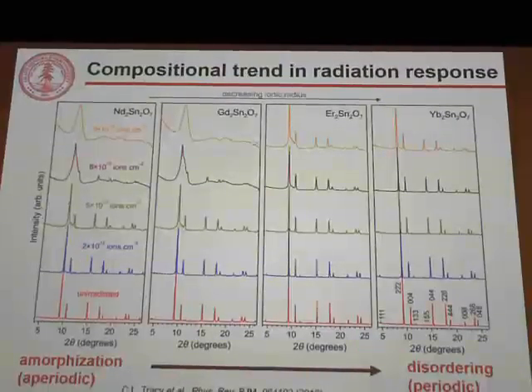Now, there is a strong compositional trend in this radiation tolerance. If we substitute the A site cation in pyrochlores with a large lanthanide, then you see at high ion fluence we have these broad diffuse XRD scattering maxima, which are indicative of an amorphous material. So some pyrochlores do amorphize under irradiation. However, if we substitute smaller lanthanides, such as ytterbium, onto the A site, they will retain their crystallinity by accessing this pyrochlore to fluorite disordering mechanism.